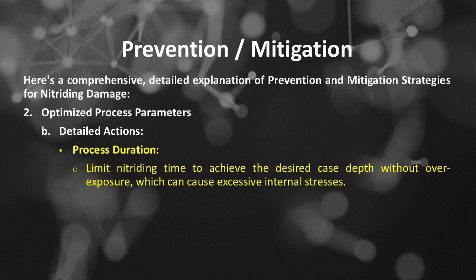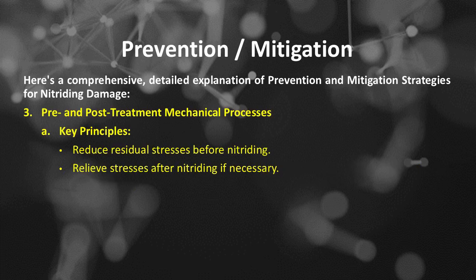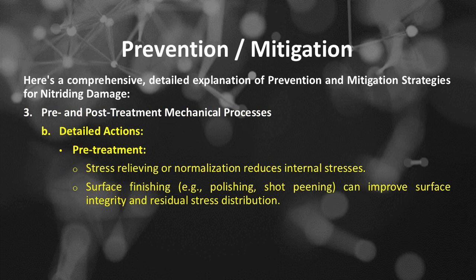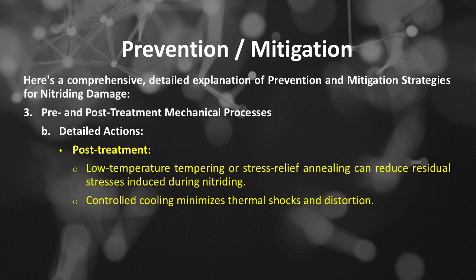Number 3 of prevention and mitigation strategies for nitriding damage is pre- and post-treatment mechanical processes. The key principles include reducing residual stresses before nitriding and relieving stresses after nitriding if necessary. Detailed actions in pre-treatment: stress relieving or normalization reduces internal stresses, and surface finishing, such as polishing and shot peening, can improve surface integrity and residual stress distribution. Detailed actions in post-treatment: low-temperature tempering or stress relief annealing can reduce residual stresses induced during nitriding. Controlled cooling minimizes thermal shocks and distortion.